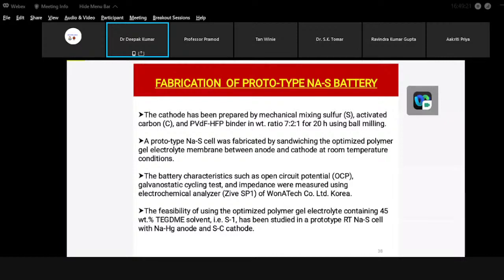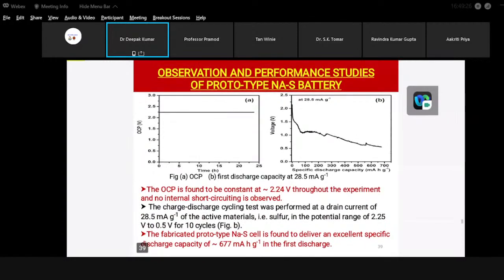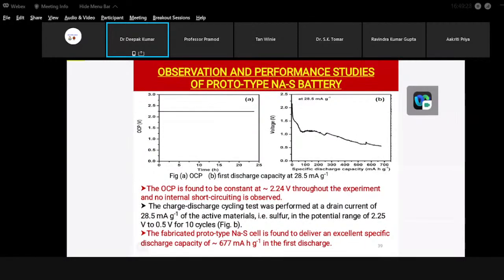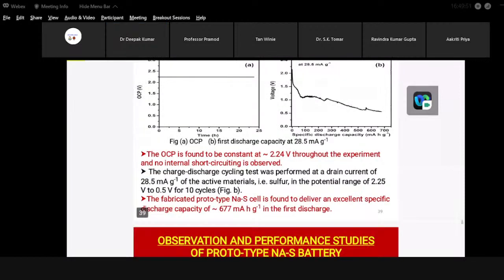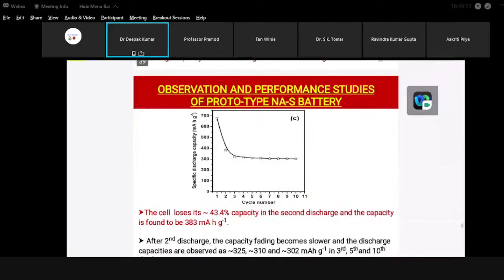Further, the prototype studies have been performed, and this is the profile which we have observed for the OCV. You can see an OCV of almost 2.2 volts is observed, and that remains almost constant. If we see the discharge capacity, it is good, more than 670 milliampere hour per gram of the active material. Further, we have seen the discharge capacity as a function of cycles also.